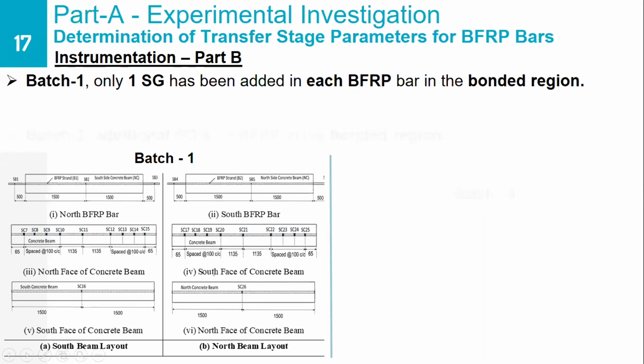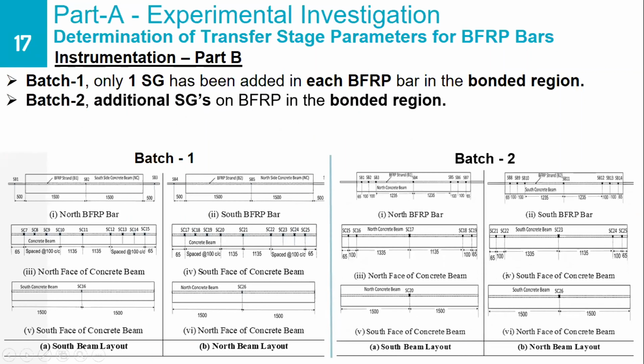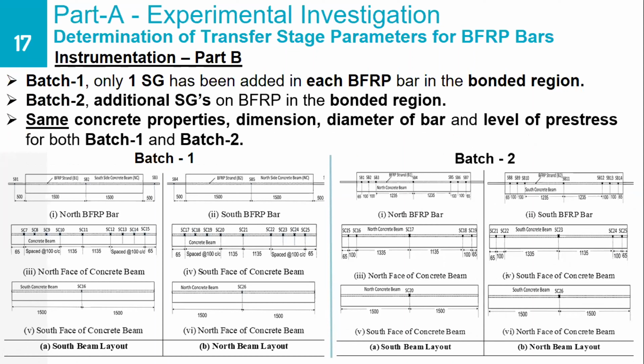A second arrangement of the strain gauges has been provided in the second batch of specimens that was cast. So this has additional strain gauges on the BFRP bars itself, because here we wanted to obtain the strain profile from the BFRP bars in addition to obtaining the strain profile from the concrete beam specimens. However, please note that the concrete properties as well as the dimension of the specimens and the bar and the level of pre-stress that have been applied in these two batches are the same.